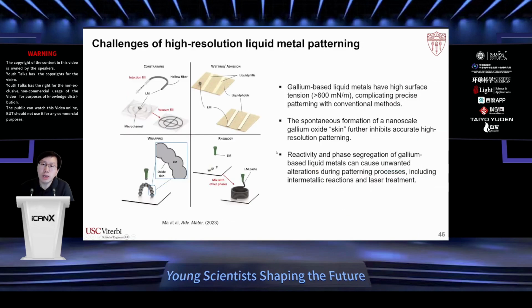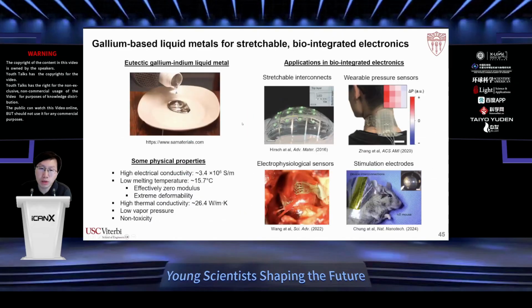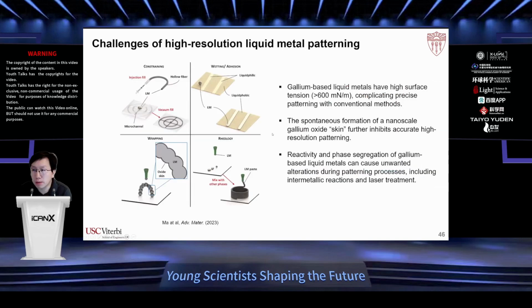But one challenge that remains is how can we pattern this gallium-based liquid metal at high resolution, because we can't use photolithography to pattern them into micro or nano scale. The reason is that this gallium-based liquid metal has extremely large surface tension, almost 10 times the surface tension of water. This complicates the patterning, as you can see from the previous video. It really tends to bead up instead of spreading out into thin films. Also, in ambient air, it forms a skin, which is gallium oxide. This makes it even harder to pattern.